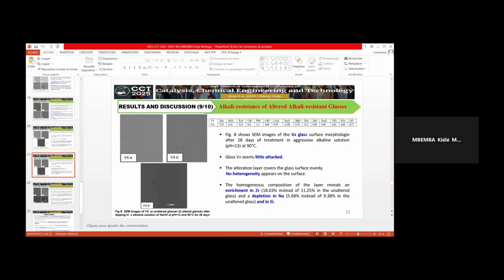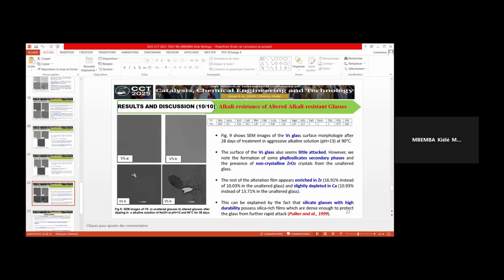and in silicon. And the last glass, the V5 glass, we can see this glass is also little attacked. We can note the formation of some secondary phases and the presence of non-crystalline zirconium oxide crystals. The layer is also enriched in zirconium, 16% instead of 10% in the reference glass, and slightly depleted in calcium, 11% instead of 13% in the reference glass. This can be explained by the fact that silicate glasses with high durability possess silica-rich films which are dense enough to protect the glass from further rapid attack.